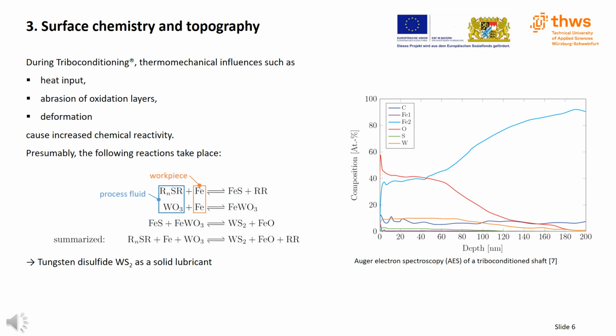The tribochemical reactions shown are equilibrium reactions, occurring in regions of sufficient energy input. The tungsten disulfide represents the solid lubricant incorporated in the tribofilm. In the Auger electron spectroscopy of a triboconditioned shaft, shown on the right, small but relevant amounts of sulfur up to 120 nanometers are detectable. This corresponds to the thickness of the tribofilm.